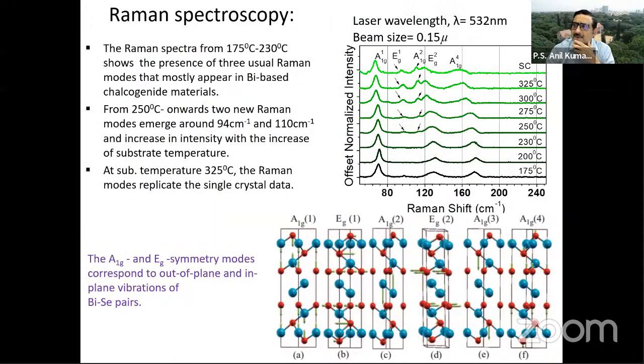An important parameter that we use to quantify the quality of the film is Raman spectroscopy. The topmost spectrum is the Raman spectrum from the single crystal, which I was showing you earlier. So we get this Raman spectrum like this. And if you look at the substrate temperature, when you grow the thin films, you get a spectrum like this. As you increase the substrate temperature, you see that around 300 to 325, this Raman spectrum matches exactly with the Raman spectrum of a single crystal.